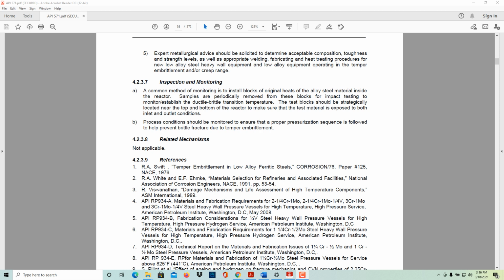Inspection and monitoring. A common method of monitoring is to store blocks of original heats of the alloy steel material inside the reactor. Samples are periodically removed from these blocks for impact testing to establish the ductile brittle transition temperature. The test block should be strategically located near the top and bottom of the reactor to make sure that the test material is exposed to both inlet and outlet conditions.